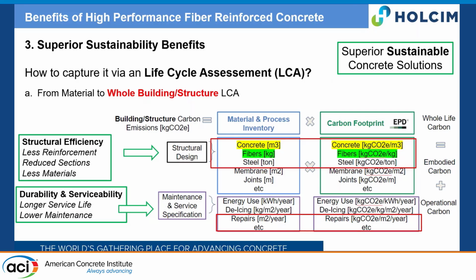Now, how can we capture those benefits in terms of LCA for this material? But this is true for any fiber reinforced concrete. I don't know if you are familiar with the whole building LCA. Typically, you run the analysis not at the material stage, but on the whole building, on the whole structure. So the first step is to do a material inventory. You look at how much material you have in your structure, in terms of cubic meters of concrete, amount of fiber, amount of steel, and so on, and then you multiply that by the respective carbon footprint. So when you have superior structural efficiency, that means you're normally going to need less material, less reinforcement. That's where you're going to use it.